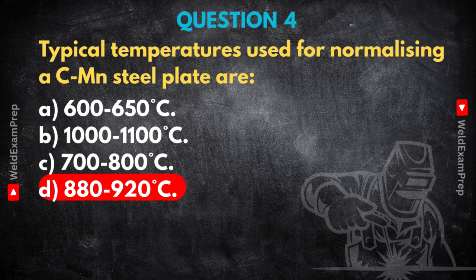Exactly. You heat it up until the entire structure transforms into austenite. Once it's soaked at that temperature long enough for the whole piece to reach it, you then take it out of the furnace and let it cool in still air. That air cooling is slower than, say, quenching in water or oil, and this relatively slow cooling allows a fine, uniform mixture of ferrite and pearlite to form from the austenite. It's this fine, uniform grain structure that gives you the improved toughness and ductility you're looking for. If you go too low with the temperature, you won't fully transform to austenite. If you go too high, the grains might start to grow too large, which actually hurts toughness. So that range is the sweet spot.